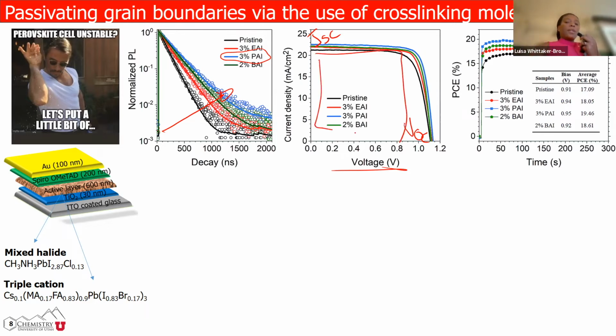And then we have the squareness of this data, which we call the fill factor, and it is the affinity of all the interfaces, how much all those interfaces like each other. So the more square it is, it means that they match each other very well. Typically, you will never get anything higher than 80% of likeness. So it's like a marriage. You will never get a marriage that is 100% likeness. So the theoretical fill factor of a marriage is 80%. It's the same thing with solar cells. So what you do is multiply these three things, and then you get your power conversion efficiency, the amount of solar energy that you convert into electricity.